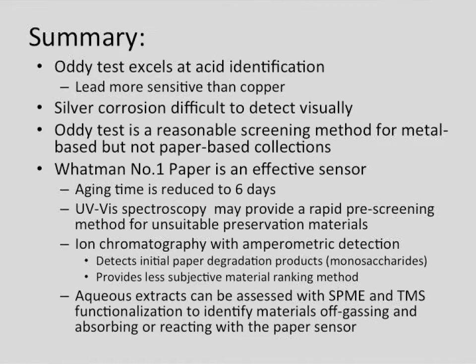I can rip through 50 Oddy test samples in an afternoon by looking at them, but I can't do that with an ion chromatography system. I can do maybe 6 to 10 in a day if I'm lucky. And it takes me all day. So we propose UV-Vis as pre-screening, so we don't have to do as many of those. And again, that needs to be corroborated with a lot more data, but we so far like what we see.